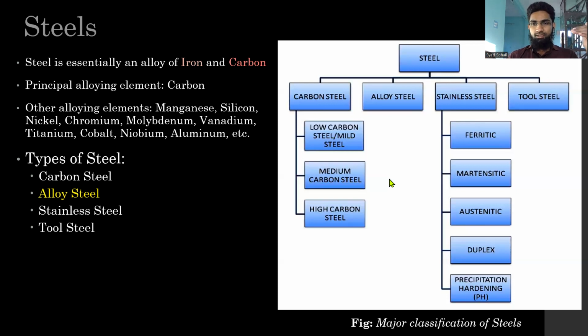Precipitation hardening stainless. These also possess ultra high strength because of the precipitation hardening mechanism. And the noteworthy feature here is that precipitation hardening is also the underlying mechanism of maraging steel. Maraging steel also relies on precipitation hardening to gain its high strength, although there is intermetallic precipitation going on. So it is similar, but the high strength that is achieved along with high toughness is what gives the uniqueness to the maraging steel. So we'll see a comparison of how maraging steel compares with other precipitation hardening steels. And in the last category, we have tool steels.